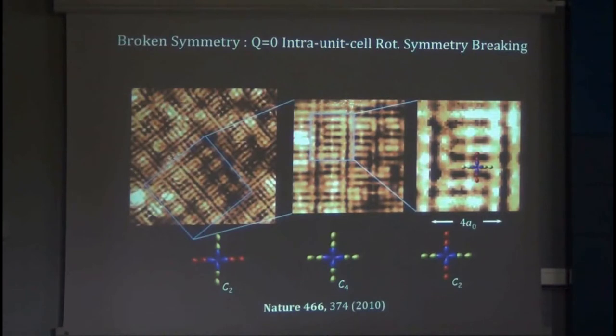Okay, anyone know what the other broken symmetry is? Well, it says it here. If you look inside the unit cell, there's a copper atom here, and there's oxygen, oxygen, oxygen, oxygen. Or let me go up here and do it. So there's a copper atom here, oxygen, oxygen, oxygen, oxygen. In terms of the image of the electronic structure, the unit cell should have had C4 symmetry. Geometrically, it has 90 degree rotational symmetry. But if you image the wave functions, it has 180 degree rotational symmetry, right? All of these objects are symmetric under 180 degree or C2 rotations.